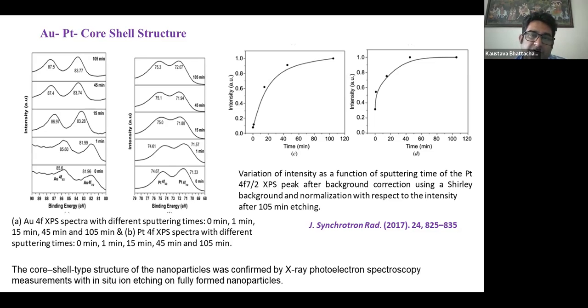If we do sputtering and XPS together, what we find is that initially, as XPS is surface sensitive, the shell gives me the XPS spectra, and after some sputtering time I get the spectra of the core also. So the amount of sputtering required before I start getting the spectra of the core can suggest how the core shell is being produced.